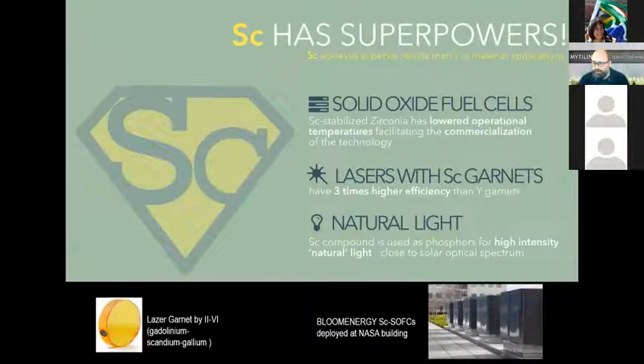But it's very interesting, because as you can see, it has superpowers. It is in fact a replacement for yttrium. It can replace yttrium in most material applications, providing better results. Most notably, in the case of solid oxide fuel cells, when yttrium stabilized zirconia, which was the solid electrolyte layer, was replaced with scandium stabilized zirconia, this allowed lowering the operational temperatures by 300 degrees, making this solid oxide fuel cell technology viable to be commercialized.